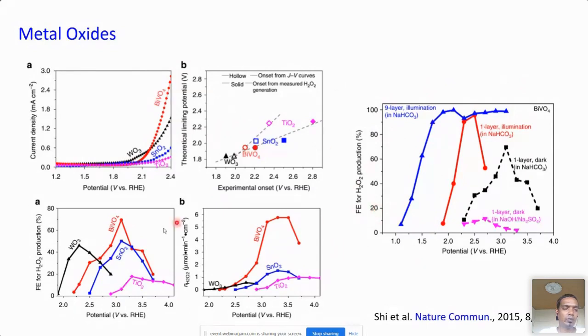As you can see, when applied as just an electrocatalyst, it produced hydrogen peroxide with a selectivity of 70%, but when they applied light, the selectivity improved beyond 70%, almost touching 100% around 2.25 volts. This gives us hope that we are not far from designing materials which can selectively perform 2-electron oxidation by suppressing the 4-electron oxygen evolution reaction, giving us a safe and greener path to produce truly green hydrogen peroxide.